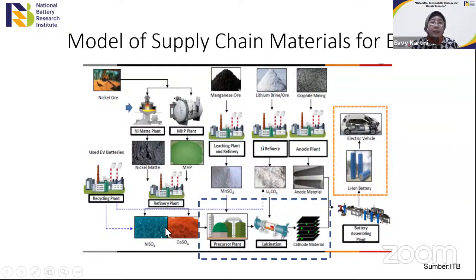webinar, and it has to be processed to become sulfate, nickel sulfate or cobalt sulfate. So it contains the nickel and cobalt, but you still need the manganese. So you need the support from the manganese ore to become manganese sulfate. If you have these three, you have the precursor plant, and then you can make the precursor, and then you add the lithium carbonate.